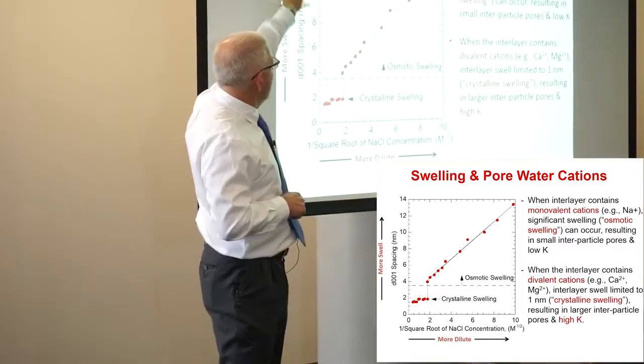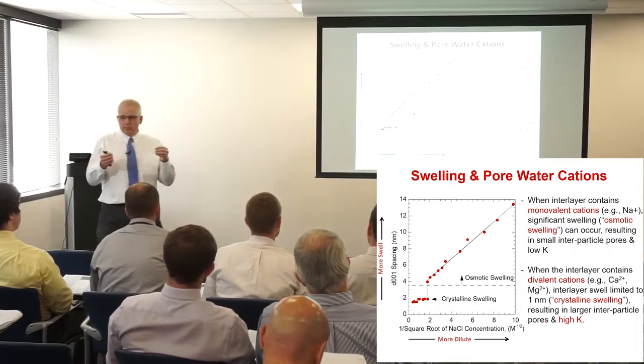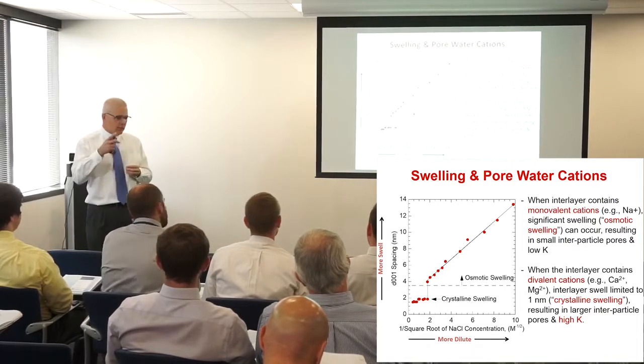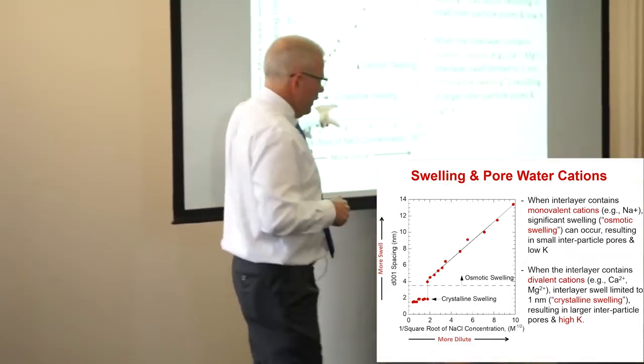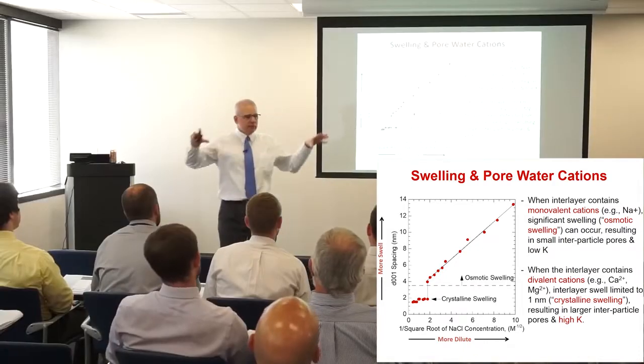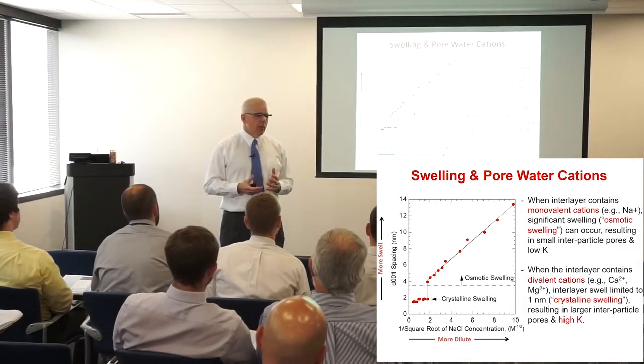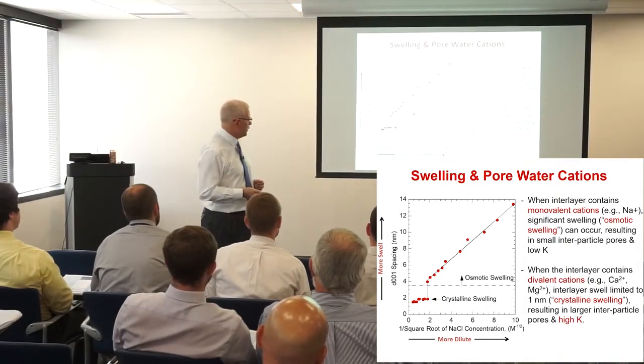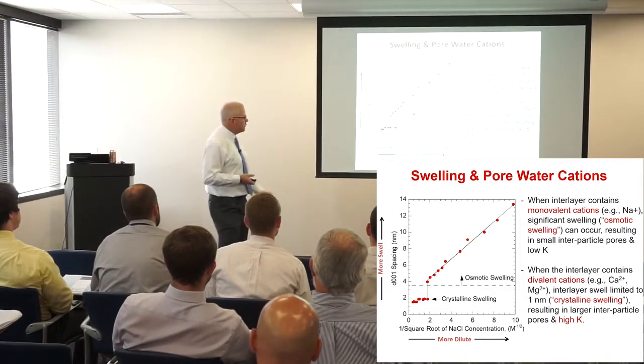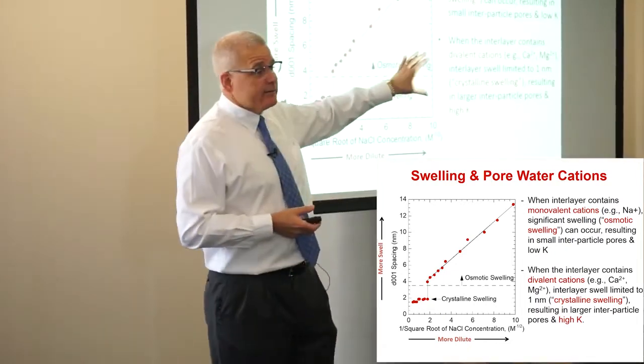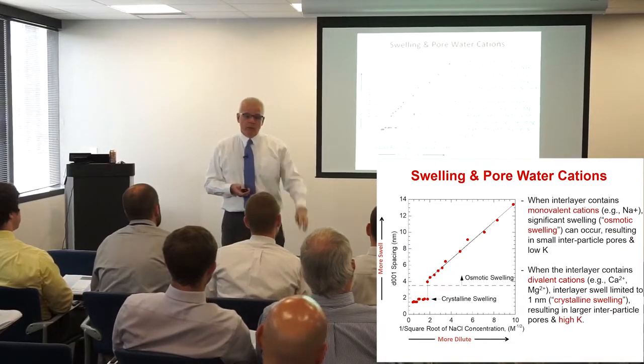The y-axis shows low swell to high swell. What Norrish was able to show — and this is a seminal finding with montmorillonites — is that swelling occurs in two phases. The first phase is called crystalline swelling, when you have the first four layers of water associated with the mineral surface. That happens under essentially all conditions with montmorillonite; you get a coating of water around the particle. Then the inner layer space opens up and we get so-called osmotic swelling. That's the stuff that makes bentonite magic — it gives it that greasy, swollen material.